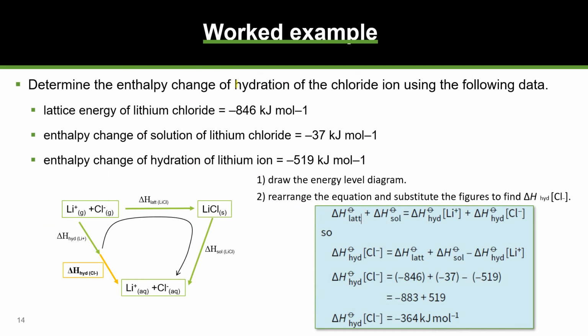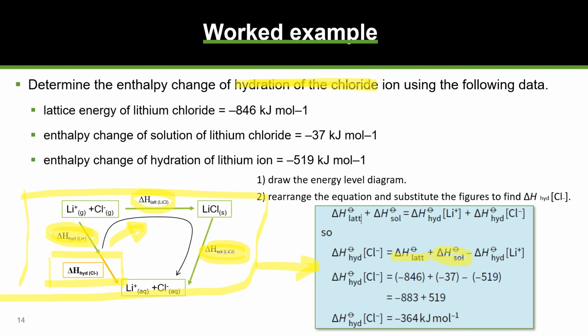Okay, in this case, we are going to calculate the enthalpy change of hydration of the chloride ion using the lithium chloride lattice enthalpy, the enthalpy change of solution of the lithium chloride, and the enthalpy change of hydration of the lithium ion. When we build up the cycle, the Hess cycle, we can use a Born-Haber cycle also, but with this one, it's maybe much simpler for you to understand. We can calculate the delta H of hydration of the chloride ion. On the right, you have the math. The lattice enthalpy doesn't change the sign. The enthalpy change of solution doesn't change the sign either. And the delta H of hydration of the lithium, since the arrow is going in the opposite direction, we are going to change the sign for that. In this case, we can calculate that the enthalpy change of hydration of the chloride ion is negative 364 kilojoules per mole.